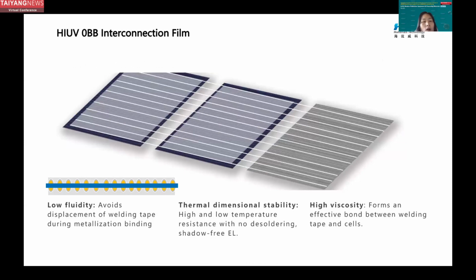For HIUV, we mainly focus on the interconnecting film of 0BB. First, it has to have a low fluidity when forming the metallization binding. Second, the thermal resistance, no matter high temperature or low temperature, no desoldering. Third, it should have a high viscosity. The welding tape and the cell should have a good fit and bonding.